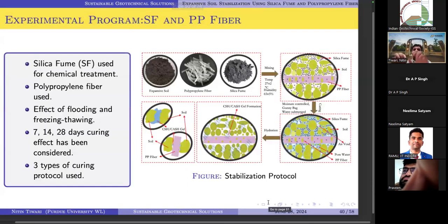Okay, so let's talk a little bit about the mechanism. You have expansive soil, you add polypropylene fiber and silica fume inside. You mix them well and keep it in the humidity chamber. In general, you have big soil particles, you have a fiber, and at the same time you have silica fume inside. The moment you do curing, the curing plays a very important role. We use three curing systems: moisture control curing, gunny bag curing, or water submerged curing.